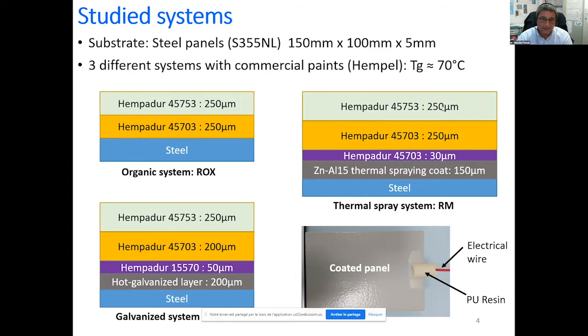with commercial paints that were applied onto steel panels. So the first system, which is called organic system, ROX, is constituted by two organic coats onto the steel substrate with a total thickness of 500 micrometers. We've got the second system, which is the galvanized system, called RG, and of course we have the hot galvanized layer with 200 micrometer thick and three different coats with a total thickness of 500 micrometers.